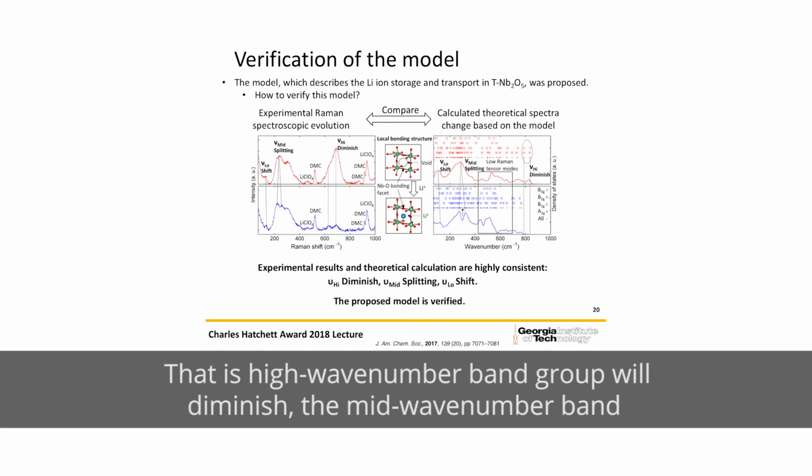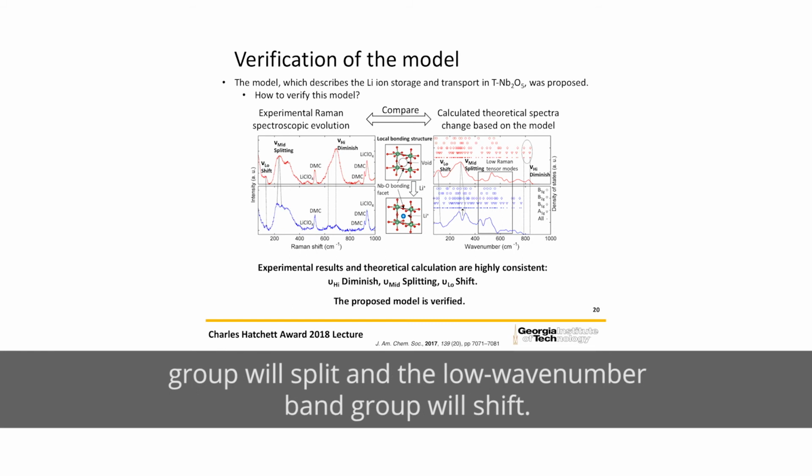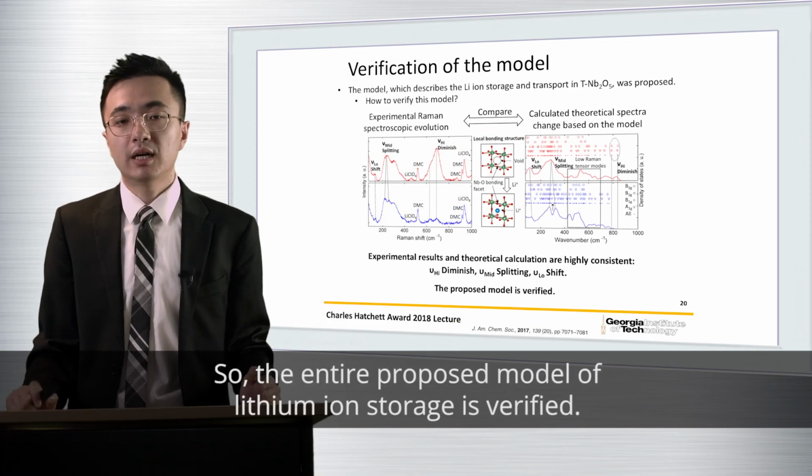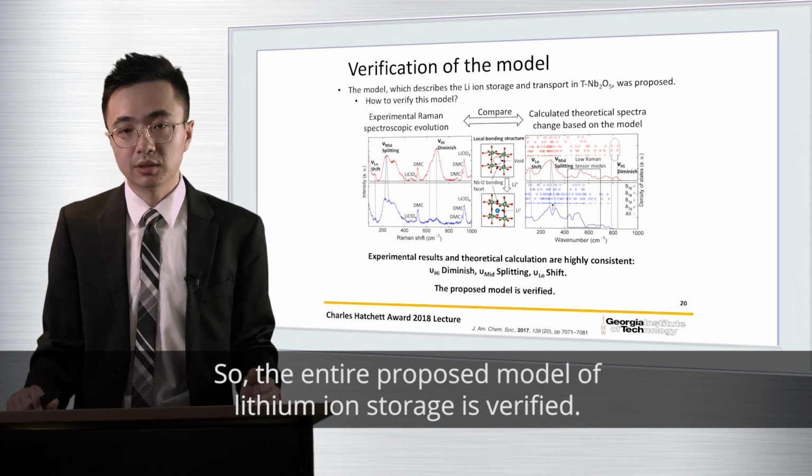So the experimental results and the theoretical calculation are highly consistent. That is, the high wave number band group will diminish, the mid wave number band group will split, and the low wave number band group will shift. So the entire proposed model of lithium-ion storage is verified.